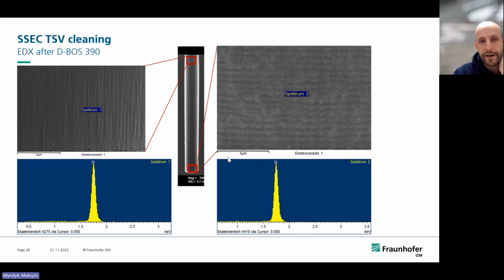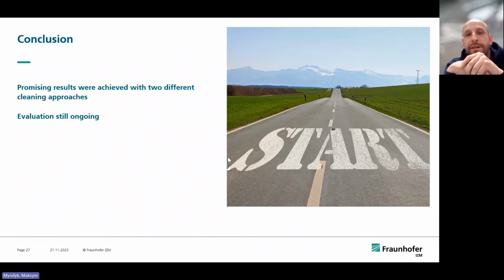But to double check it, we performed the EDX analysis. And the EDX analysis just confirmed our suggestion that the fluorpolymer was completely removed from the TSVs, and no residuals were found in this particular case. To summarize the results, I was actually very surprised to see good results. And the MACPI process still needs optimization, but it also offers other positive points like lower temperature and shorter process time.